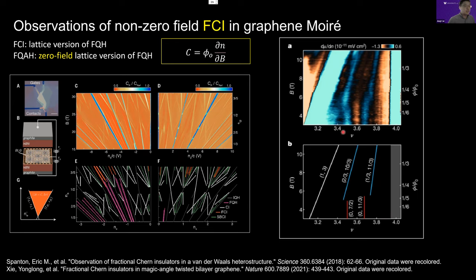And on the right-hand side, in twisted bilayer graphene, people use a scanning probe to scan over the surface and find the best position to have lower disorder. What people see is that at a very small magnetic field, at fractional filling of the Moiré superlattice, it has no dispersion at all. Basically, it's topologically trivial. But after applying 5 Tesla, a state with a finite slope of the Streda formula emerges. That's the hallmark of the fractional Chern insulator, or the non-zero magnetic field version of the fractional quantum anomalous Hall effect. So to date, there's no report of an actual zero field fractional quantum anomalous Hall effect.